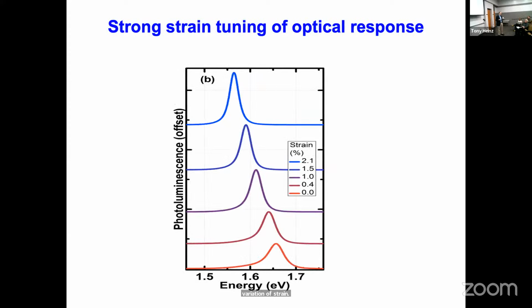So first of all, in 2D material, strain is a favorite tuning parameter because it's pretty easy to apply and it does a lot. So this is just where we apply up to 2% strain, and we look at the optical emission spectrum. As you strain it and the atoms are further apart, it shrinks the band gap a little bit. Famously, if you do things right, you can get really high strains in 2D materials, and change things even from a semiconductor to metal, things of that sort. But what's also very distinctive about strain in 2 dimensions is you can control it in a very localized way. That's a lot harder to do in 3 dimensions.